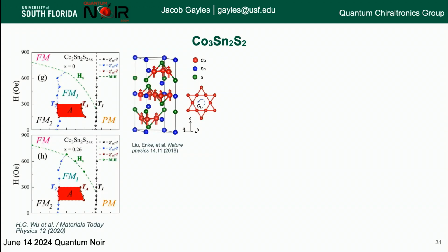And so this is, when I started my postdoc, the first week, my office mate wanted to find skyrmions in this material. And what I did was I looked at the symmetry and I said, not possible, it doesn't break inversion symmetry. And so I was off the project there, but then what he did find was those Weyl points in the material, and it became a very big paper in a very nice Nature Physics journal, and has done very well for the material.